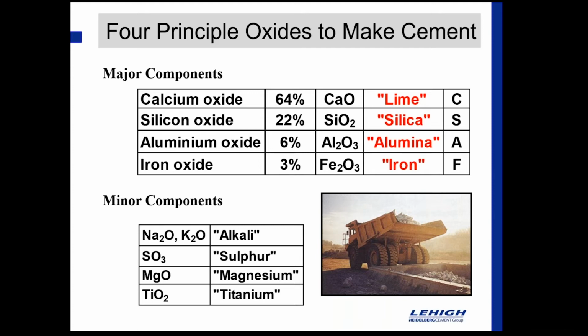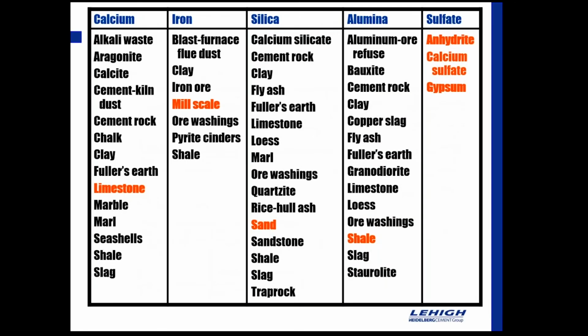And so where you get those four major components can come from a variety of different places. You might get your calcium around here. Like I said, primarily it's going to come from limestone. That's one of the reasons why you see cement plants in our area, because we're blessed with a lot of limestone deposits. Iron can come from different places. I've seen it come from pyrite and mill scale particularly. Silica, again, primarily sand. The alumina source, at least in the Mitchell plant, is shale. And sulfate can come from either pure gypsum, anhydrite, calcium sulfate, whatever that might be. You have to have that sulfate, and we'll talk about why in just a bit.